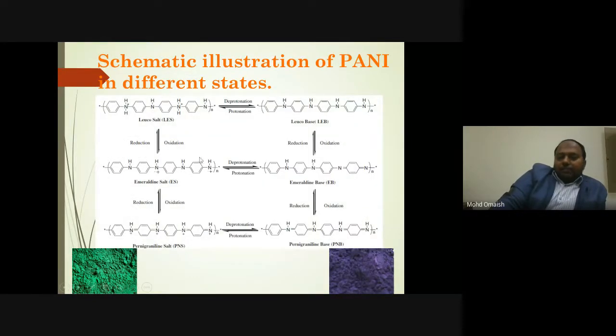In the case of polyaniline, we have a lot of states, but there are two major states, the conductive and the non-conducting states. The conductive state is called the emeraldine salt form, the green form, and the non-conductive state is called the emeraldine base form. You can see the green and blue color, and you can easily go from green to blue by simple acid-base chemistry. For example, if you have the emeraldine salt form, you can treat it with some base, neutralize the acid, wash, and get the base form, which is the non-conducting form. And if you have the base form, you can treat it with some acids or any anionic dopant and get this green form. So the conductivity can be easily tuned.